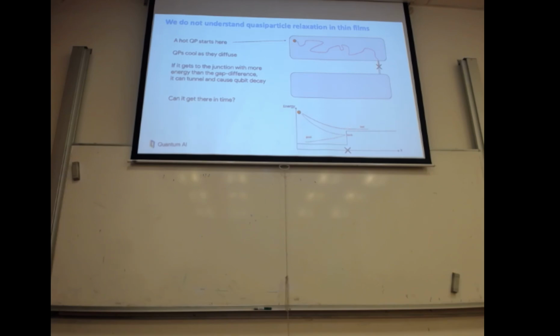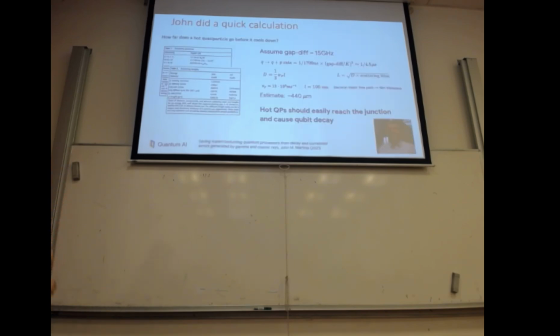So Martinez was saying that it looks too good, it's not possible, because if this aluminium is clean, then the diffusion distance of this hot quasi-particle is very big. And indeed, John, in his paper on saving superconducting quantum processors from decay and correlated errors generated by gamma rays and cosmic rays, did some estimate of the typical distance that a quasi-particle goes.